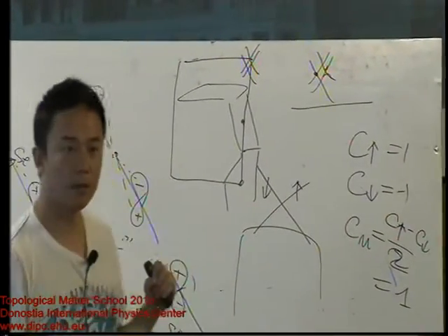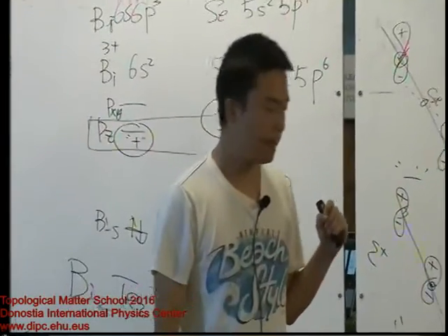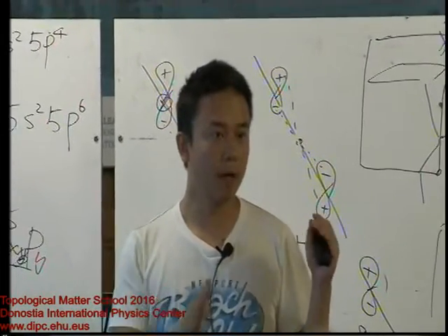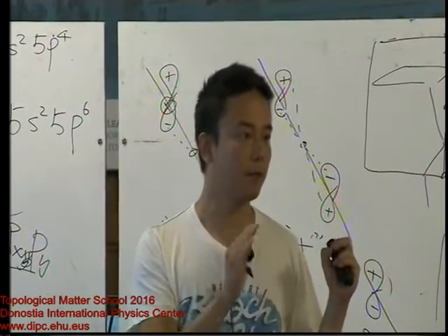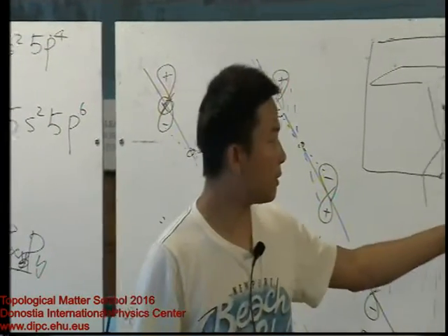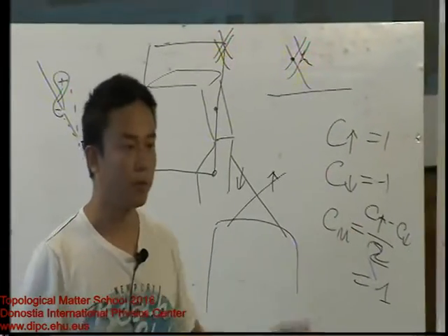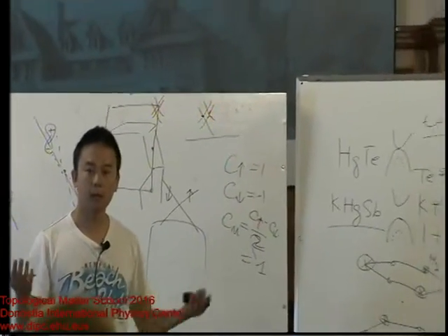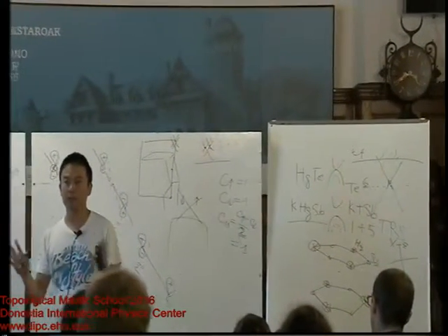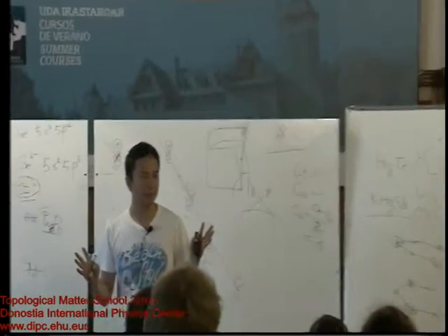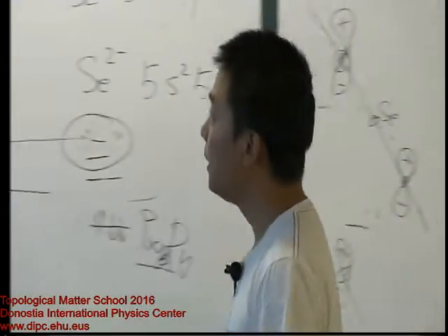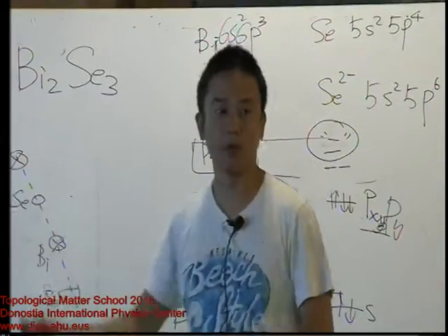And then I just want to make it clear that if we have inversion, then we will have surface states. Whether this surface state is robust just depends on whether there is a symmetry to protect it. For the topological insulator, it's time reversal symmetry. If it's not a topological insulator, the Z2 is trivial, there are two inversions, maybe there's some additional crystal symmetry protection. And this will really depend system by system. And here is a case of mirror symmetry protection.